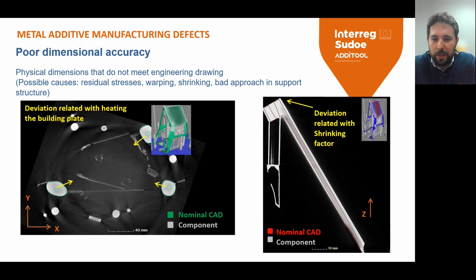Okay, other example is the image on the left. This is also a CT scan while the part is still on the plate before extracting the supports. We detect deviation again from 0.5 to 1 millimeters between interfaces that are these legs. Okay, they move to the center of the plate. And these deviations were related with the expansion coefficient of the substrate, which was from an aluminum alloy.